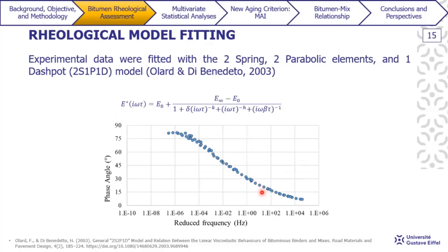The linear viscoelastic model used here to fit the experimental data was the 2S2P1D model, or two springs, two parabolic elements and one dashpot, proposed by Olard and Di Benedetto, which here is represented by this red line. And we can see that it fitted the experimental data quite well. For bitumen, we consider that the static modulus E0 is zero.